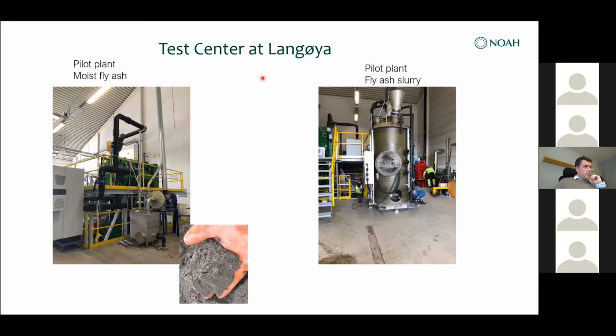At Langøya, we have a big, large test center where we do a lot of things. When it comes to CO2 process, we have two processes we're looking at. To the left here, we have what we call the dry fly ash. It's actually moist. We add some water to the fly ash and then mix it with flue gas. We can mimic flue gas at Langøya. We have a small incineration plant where we use wood for making CO2. And this is a very, very fast process. The kinetics in moist fly ash combined with CO2 is very fast. And here we have a picture where you can see carbonated fly ash.